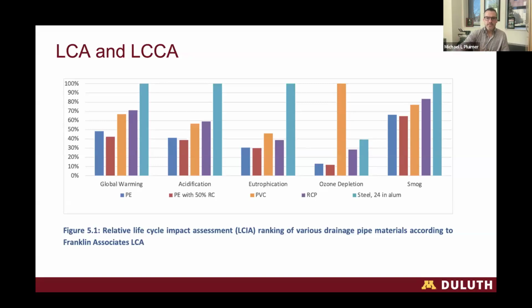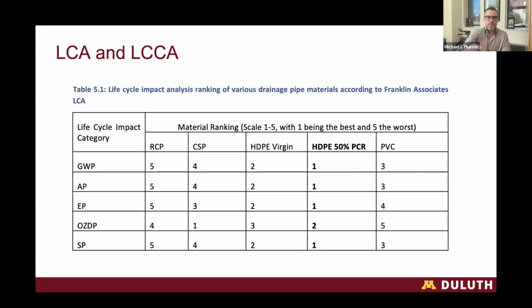And you can see in many of these categories, the pipes manufactured with 50% recycled content perform better than the other materials. And this is a scale that was published, kind of a ranking showing that the pipe in bold there on the 4th column, manufactured with 50% post-consumer recycled material, was the best performer related to global warming potential, acidification, et cetera, in the majority of these 5 categories.